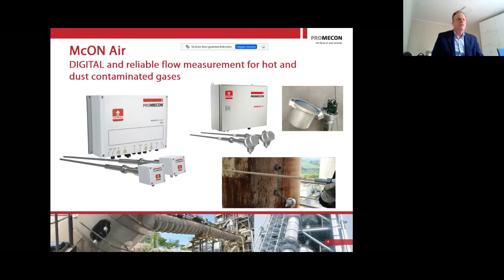This dust prevents you from taking accurate readings with delta pressure measurements, and also with others such as thermal dispersion, hot wire anemometers, and also ultrasonic measurements have huge problems in this environment. Our measurement technology is unique. We use two sensors and we use a cross-correlation technique to measure the flow velocity in your duct.